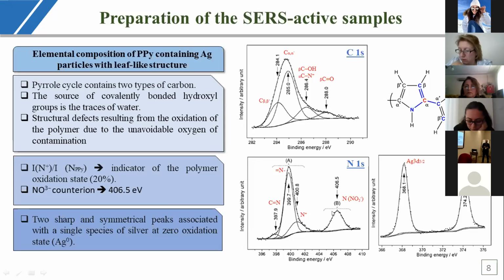The second region is the nitrogen belonging to the neutral doping anion at 406.5 electron volt. The polymer doping rate can be calculated by the intensity ratio of the nitrogen of the doping agent and the nitrogen of the polymer. It's 20% in our case, which is near the theoretical value of 33%. On the other hand, the interaction between the polymer and silver particles was confirmed by the presence of 2 doublets consisting of 2 sharp peaks associated with silver at 0 oxidation state.